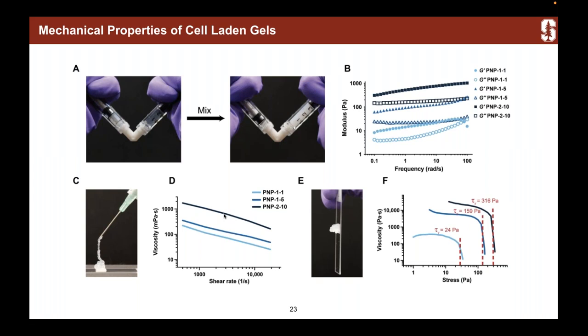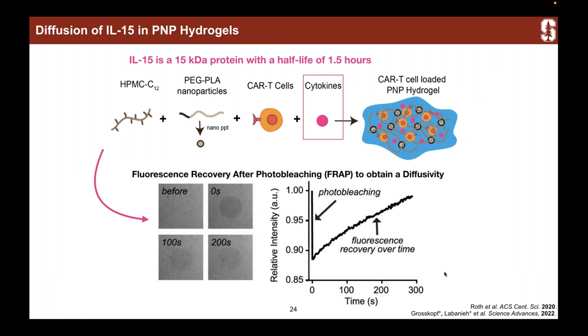We were pretty fascinated that even loading huge volume fractions of cells into our hydrogel barely changes the injectability of our formulation. We also looked at the yield stress by looking at where the viscosity falls during a flow ramp increasing stress. We formulated CAR T cells and stimulatory cytokines in our gel material — the cytokines are really there to stimulate CAR T cells to grow and proliferate. We wanted our gel to act as a proliferative niche when delivering these CAR T cells. We then wanted to understand the diffusivity of the cytokines — how quickly does the cytokine leave the hydrogel?